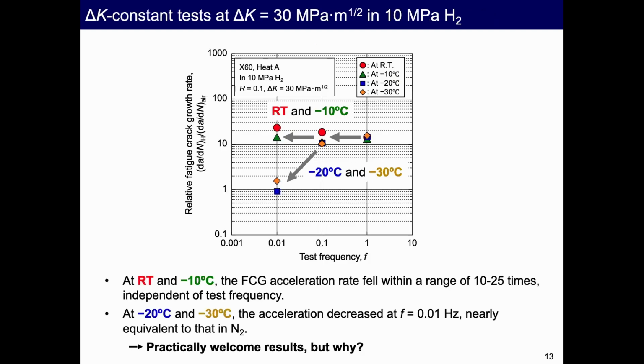Then I show you the result of delta K constant testing, that means acceleration rate as a function of the test frequency. This is a bit complicated, but interesting. At room temperature and -10 degrees C, the crack growth acceleration rate fell within the range of between 10 and 25 times, independent of the test frequency. But if we look at the result at -20 and -30 degrees C, the acceleration decreased at 0.01 Hertz, which was nearly equivalent to that in nitrogen gas. This is also good news from the practical viewpoint.